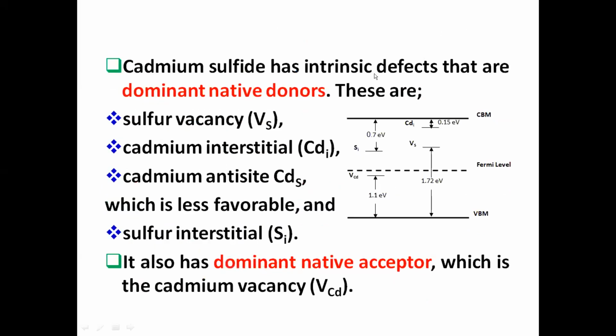Cadmium sulfide has intrinsic defects. Most of them are dominant donors, and one of them is a deep acceptor. From the donors is the sulfur vacancy shown here in the schematic. It is above the Fermi level in the conduction band. Cadmium interstitial, which is close to the bottom of the conduction band, so it is a shallow donor. Then cadmium antisite, but it is less favorable, and sulfur interstitial, here it is in the band gap above the Fermi level. And it has a dominant native acceptor which is VCd, and it is a deep acceptor as shown in the schematic.